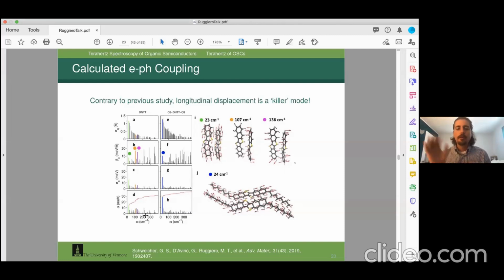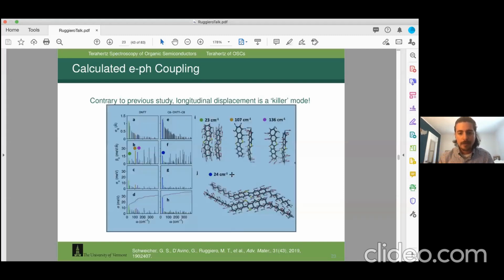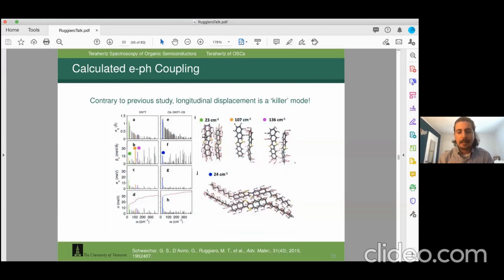What we found was that both materials exhibit this longitudinal motion, and that longitudinal motion is detrimental to electron phonon coupling, or detrimental to charge carrier mobility. As you see, this green bar is a relatively large contribution—in this case, a very, very large contribution. But what was interesting to us is that the alkylation made no difference between the 2 systems. It was almost the exact same frequency.